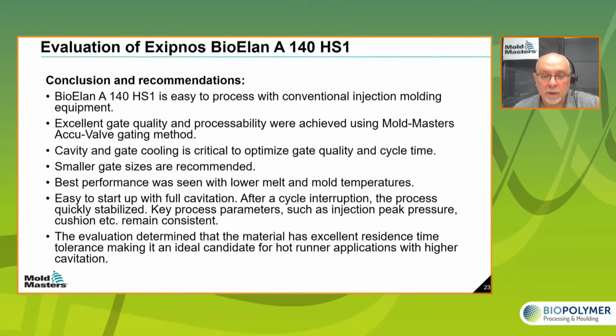1 millimeter gave us a very good gate quality with our valve gate. Our tip gate was a 0.8 millimeter gate size, which is actually still quite large and could be smaller for a tip gate. Our best performance was with a melt temperature of 150 and a mold temperature of 15 degrees.